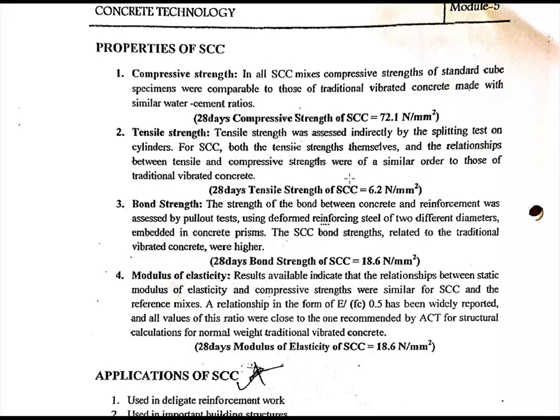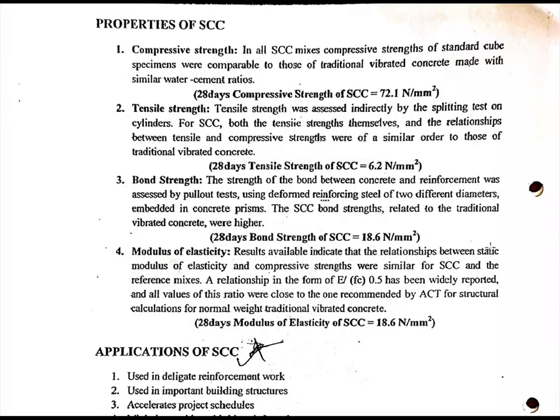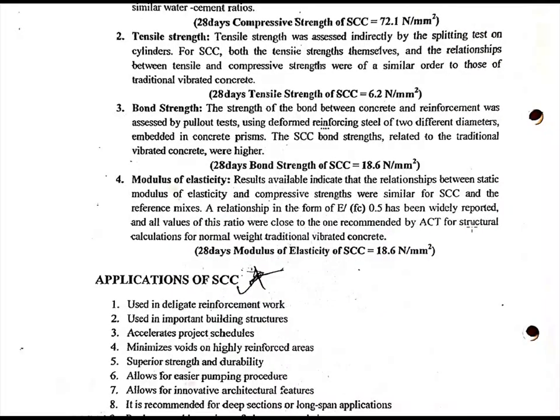Even in case of tensile strength, we will be performing the split tensile test. In the split tensile test also, we will be achieving almost the same strength. When it comes to bond strength, the bond strength is actually higher in case of self-compacting concrete in comparison with traditionally vibrated concrete. The modulus of elasticity of the concrete is also very similar to the normally compacted concrete mix.